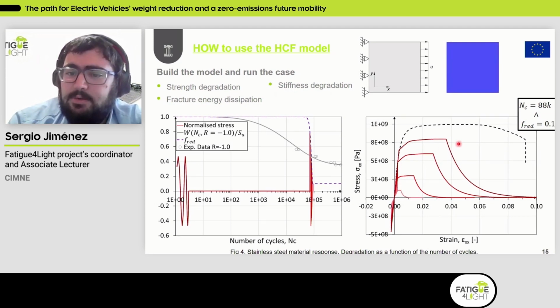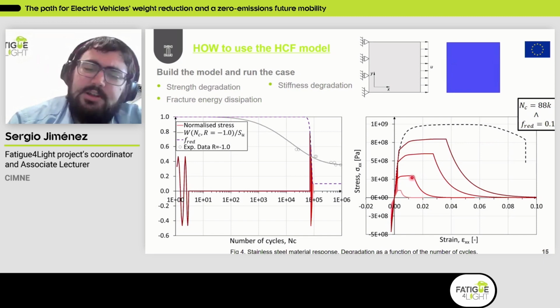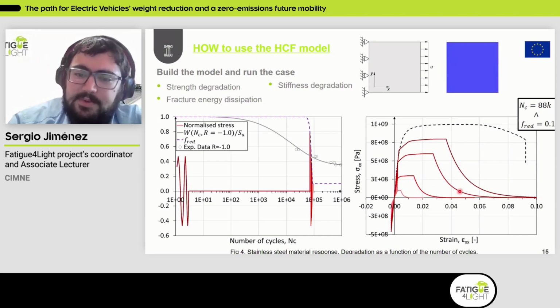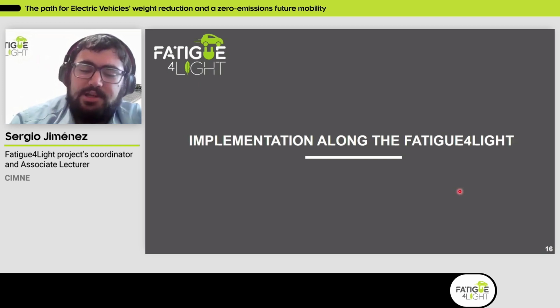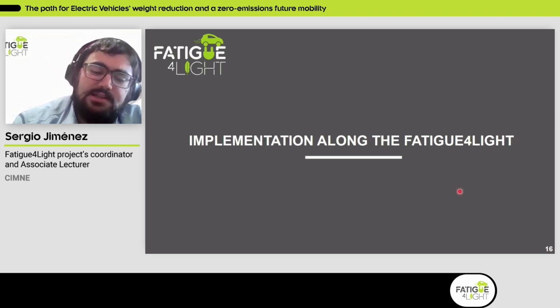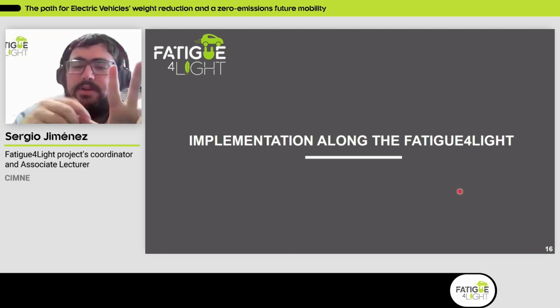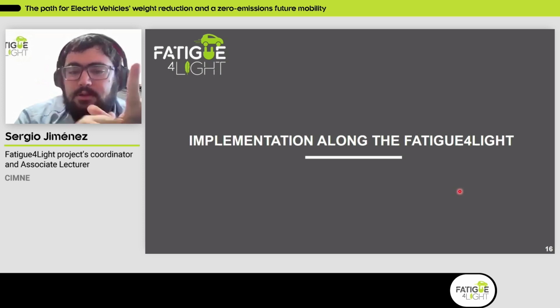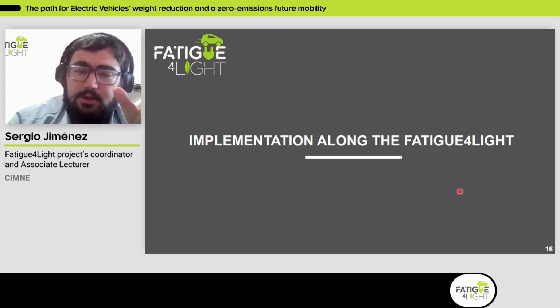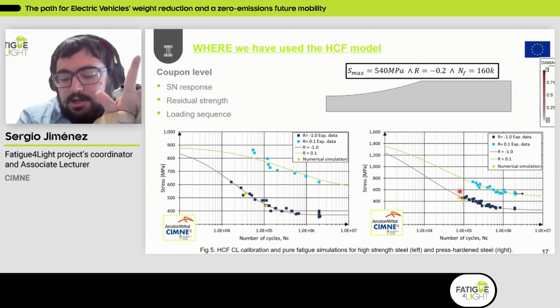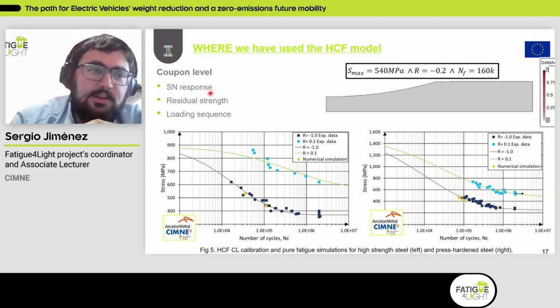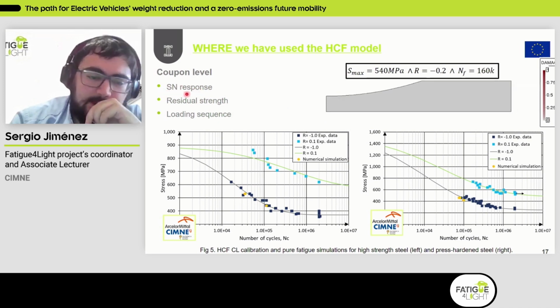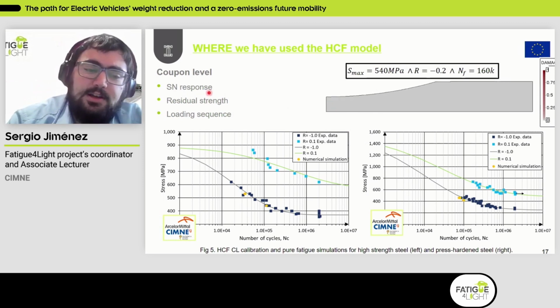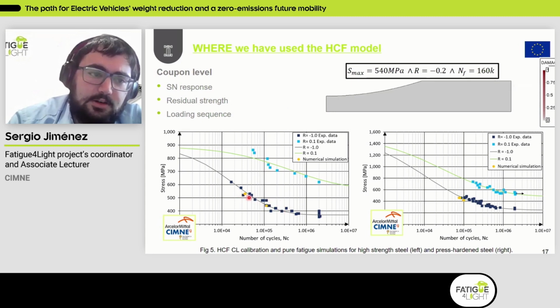And the same happens when we move to 88,000 cycles. So strength, fracture energy dissipation, and also stiffness degradation appear. So now it's time for the application of this model in the case examples of the Fatigue4Light project. So we've worked at 3 levels. We've worked, first of all, at coupon level, aiming to characterize the model itself. And in this type of experiments, we've worked basically on 3 different types of simulations, which are pure fatigue simulations, reproducing the experiments done to obtain the SN curves.